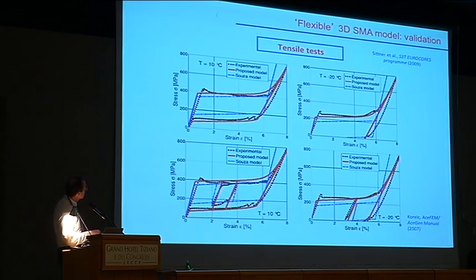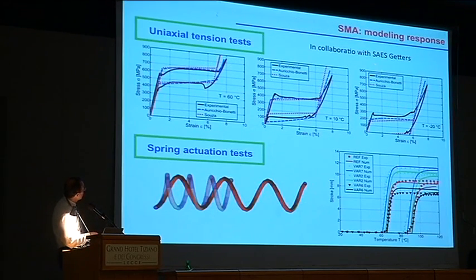We compare not only with the data produced by Professor Sittner, but we have a long-lasting collaboration with SAES Getters. SAES Getters is a company in Italy, very close to Milano, and they are the world leader producer of shape memory alloys nowadays. So we have a collaboration with them. Here you can see other uniaxial tension tests produced by SAES Getters and our comparison with their experiments. And we also calibrated the model for reproducing the behavior of spring actuation tests. And here you can see a bunch of dots with different colors. Each dot is basically a different spring or a different spring under different conditions. We calibrate the model using just one curve, and we're fully able to reproduce the behavior of the spring under different conditions. So the company was quite interested in our simulation ability.